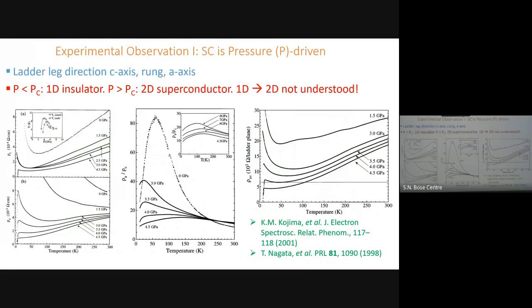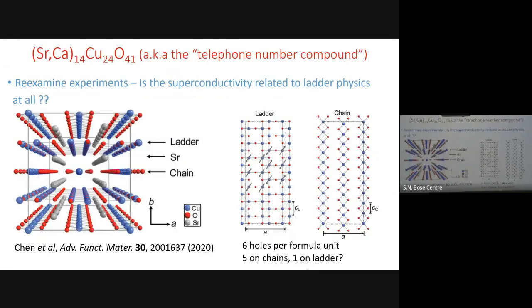The actual experiments are shown here, and I'm going to slow down considerably. The interladder direction is A. This direction is C. The separation between the layers is B. In the experiment, what you do in the layered materials, you put in holes. In the ladders, you put pressure in the B direction. So these come slightly close to each other, but up to 9.6 gigapascal, there is no change in the ladder structure. Something to keep in mind, 9.6 gigapascal.